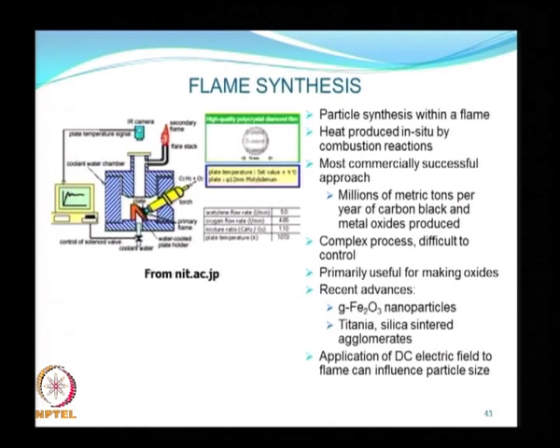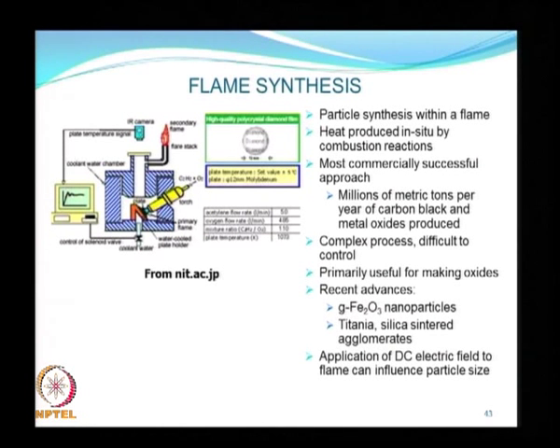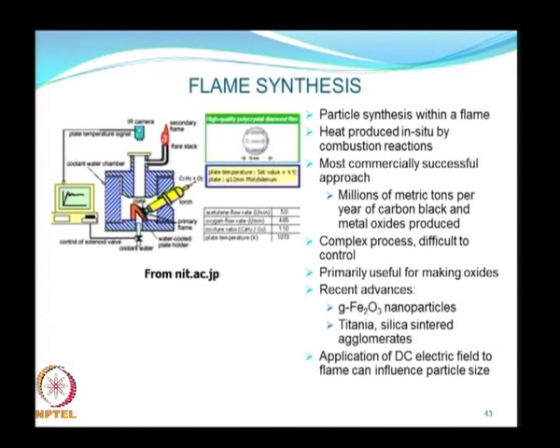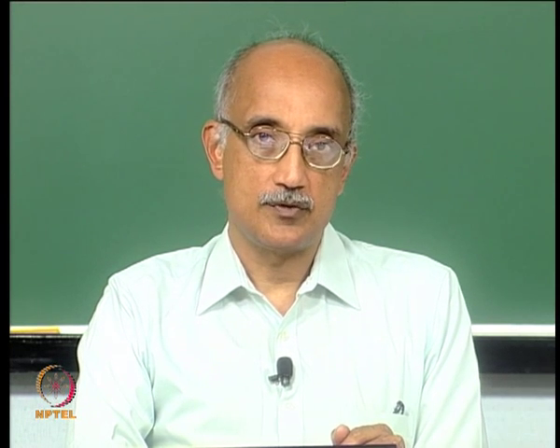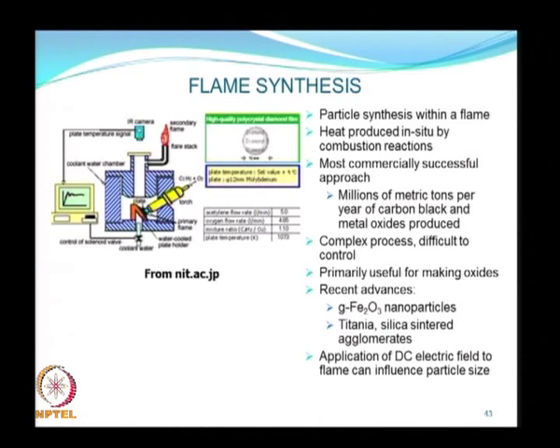The drawback to flame synthesis is that combustion is not an easy process to control. It is complex but widely used for making oxides, and recently various types of oxide nanoparticles as well as sintered agglomerates have been produced. In terms of control, it has been found that applying a DC field to the flame can stabilize the combustion reaction and produce a more tightly controlled particle size distribution.